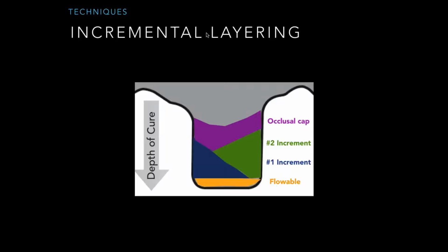polymers. The first layer was thought to wet the surface for adaptation. Most frequently placed in a Class 2 restoration, the gingival box and occlusal floor was a thin flowable layer, like you can see here in the yellow on the diagram. Remember, flowables are notoriously guilty of shrinkage because they're less filled. So the initial layer was about 0.5 to 1 millimeters in thickness. Next, increments of 2 millimeters were layered and cured. Each layer allows for the proper light penetration of the photopolymerization. However, the possibility of voids, contamination, and the time required to place these restorations are a disadvantage, and they're somewhat limiting.